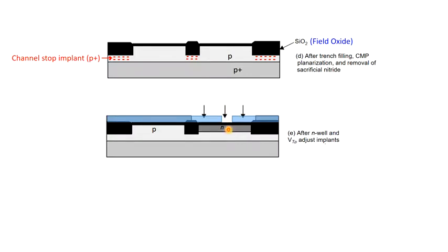Now we do an implantation only through this region, so that only under the gate the doping changes. Why are we doing so? That is because if you dope this region, the doping concentration will change, and the change in doping concentration will help us in adjusting the threshold voltage, right? So this second implant is called the threshold voltage adjustment implant, right?